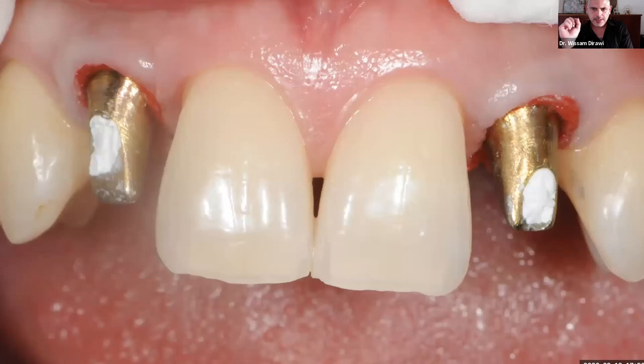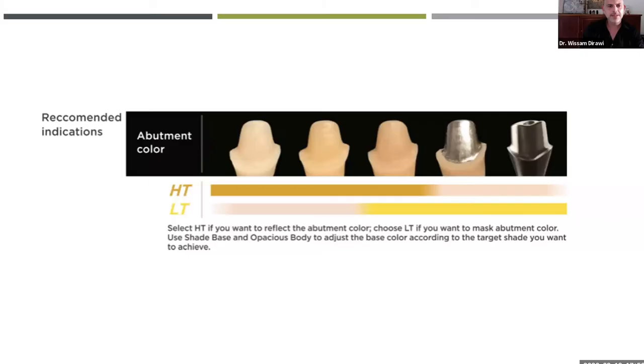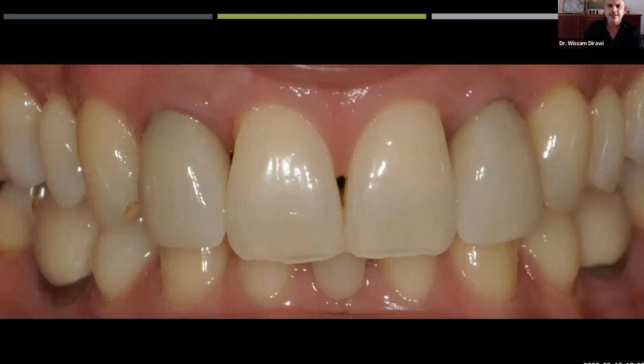This case, maybe I shouldn't show it, but I will show it anyway. We have two implants, 1-2 and 2-2, and we have to cement this one, and we have a dark or a metal abutment. And of course, we are on this scale here, but I didn't talk to my technician. We didn't have any discussion. I just said, give me the STML because it looks good in the front. And the problem is that it is too translucent. So we actually get a dark crown here. We can see the shade